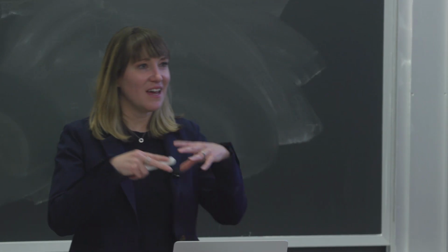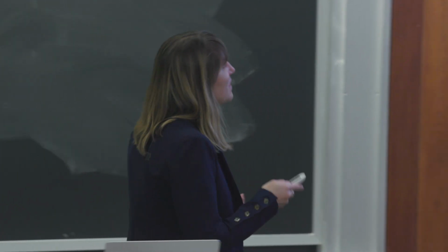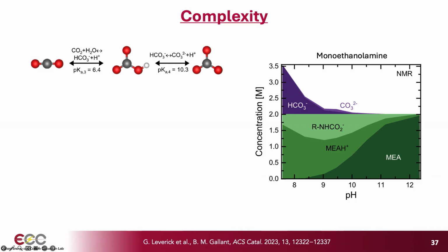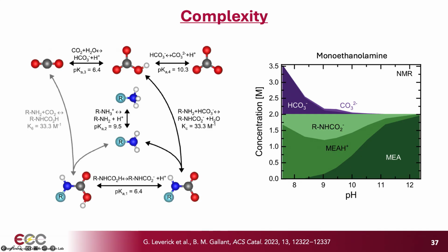So now we're looking at doing an already complex reaction, CO2 reduction, on a capture solution. When CO2 dissolves in water, even in the absence of amine sorbents, there's an equilibrium between CO2, carbonic acid, the bicarbonate, and the carbonate anion, depending on the pH of the solution. When we have the amine present, it becomes far more complicated. Now the amine can react with CO2. You can form carbamate, as I indicated on my introductory slide. The carbamate can actually react with water, and you can form bicarbonate eventually, and then there's the ammonium. So there are simply more species, and it gets a whole lot more complex.